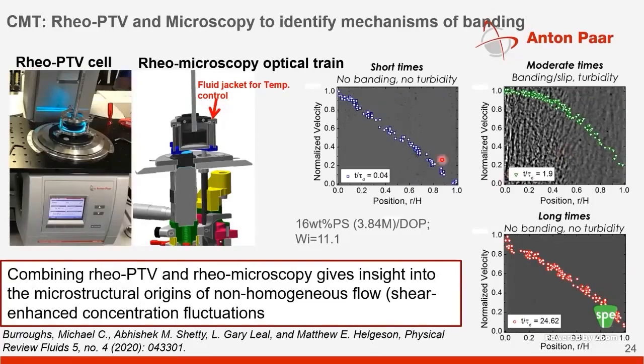This is some work where I was involved, from Matt Helgeson's group at University of California, Santa Barbara, where two different techniques were combined with rheology, namely particle velocimetry and in situ microscopy. Both PTV and microscopy were done on the samples to better understand what was happening, investigating the coupling between shear enhanced concentration fluctuations and the potential for non-homogeneous flows in entangled polymer solutions.